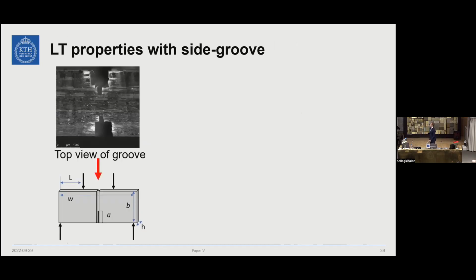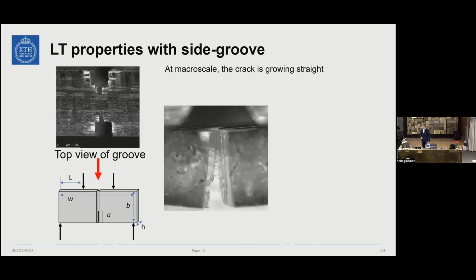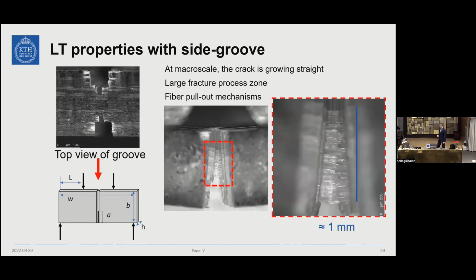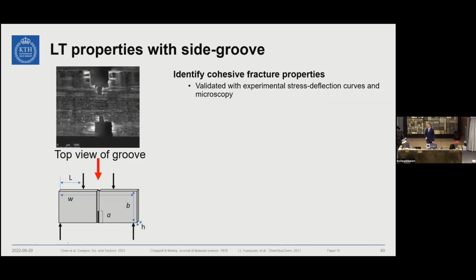If we look at the top view here, this is how we made the cross section. We used a saw to create this groove. And from microscopy, we can see that the crack is actually growing from a microscopic scale in a straight manner. However, there's a large fracture process zone where there's a lot of fiber pull-out mechanisms. Reasons for why it's so strong in that direction.